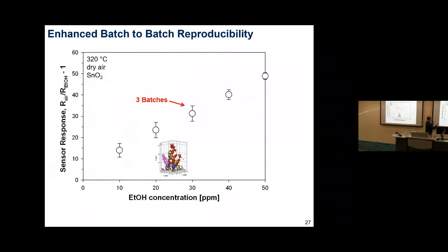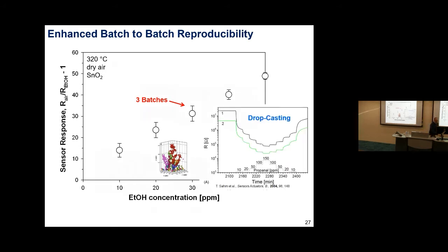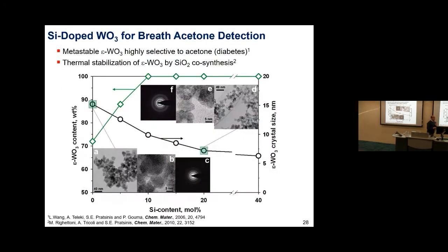Also, these are 3 batches, and this is the sensor response to ethanol. You can see that this process is very reproducible, because the self-assembly of small nanoparticles, millions of nanoparticles, is controlled by the same forces. So you get very reproducible properties. You can also use this method to improve selectivity, which is one of the major issues with metal oxide gas sensors.